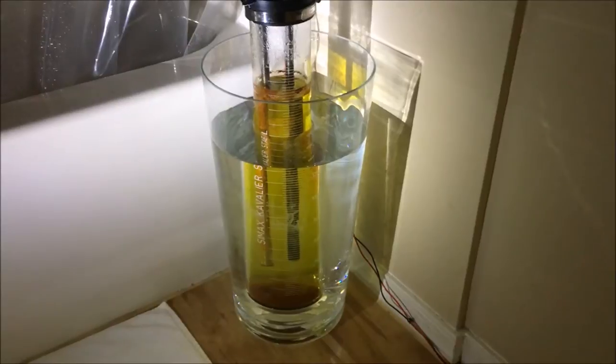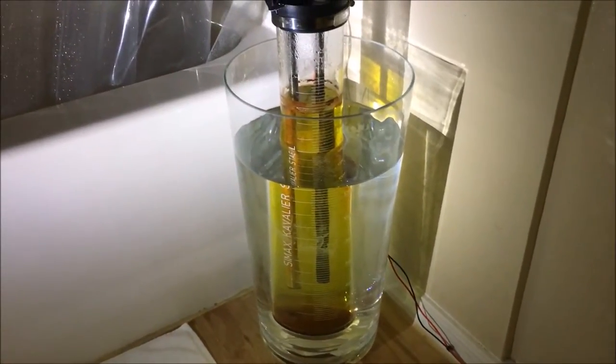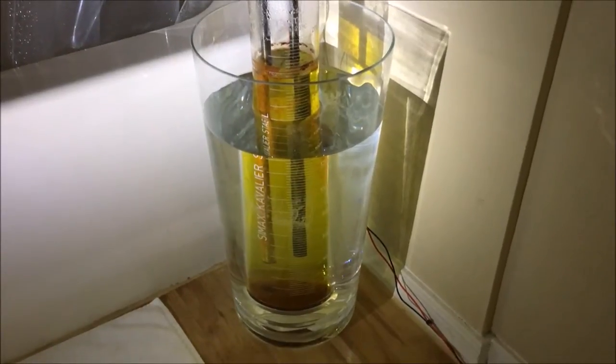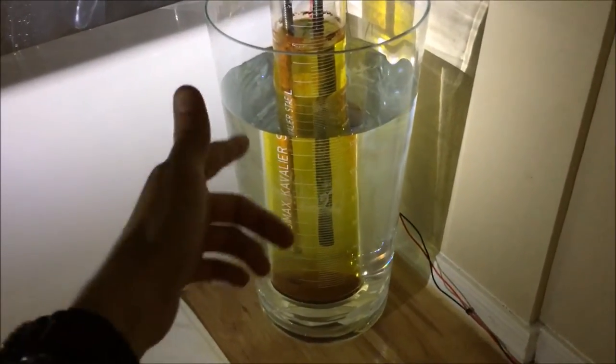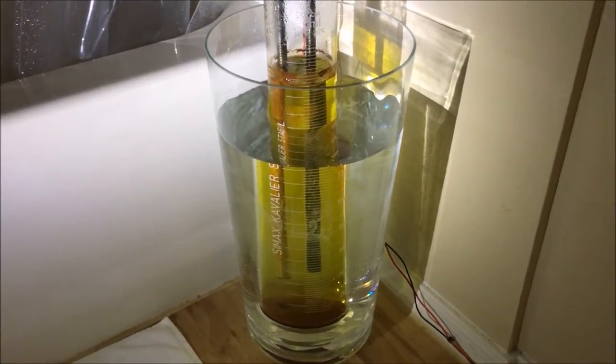Now here's the second problem that I've run into and this is more of a logistical problem. Stainless steel contains chromium and this oxide and this yellowish solution that has formed is going to be very rich in hexavalent chromium.